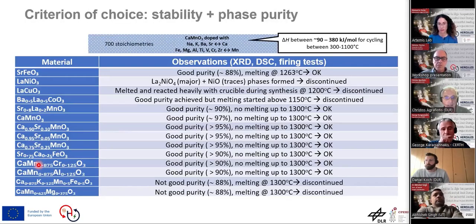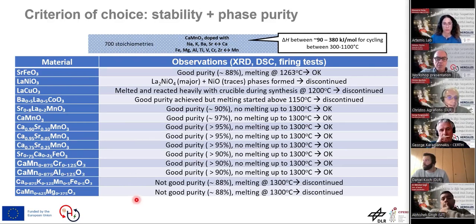And if we go now to the next slide, we see, for instance, some typical compositions that we tested on the right-hand side, and we see some of them are okay, some are melting, some suffer dissociation, and some suffer dissociation and produce different phases on the perovskite. Some of them have good purity, they are stable up to high temperatures, and so on. We proceed with the families of cation dopants and basic elements that more or less do not present any such problems of phase stability or melting or dissociation.